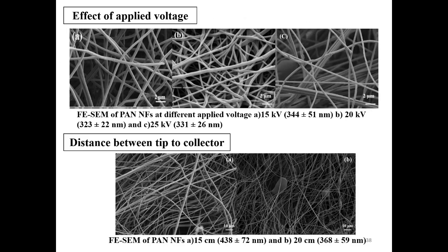When we apply the voltage, what will be the change in the fiber size? These are the field emission scanning electron microscopy images of PAN nanofiber at different applied voltage. 15 kilovolt gives 344 nanometer, 20 kilovolt gives 323, and 25 kilovolt gives 331. Not too low or too high. So 20 kilovolt is the optimized voltage where the fiber can be drawn at 323 nanometer.